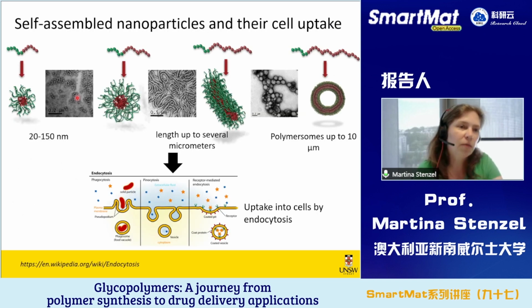But what is even more interesting when we use block copolymers is that we can tailor the size and the shape. So if we start off with two small blocks, we might get very small micelles, like shown here in that TEM. If we make this hydrophobic block longer, we end up with bigger micelles until we come to a point where we obtain cylindrical micelles. So now we get elongated structures, or if we make the hydrophobic block even longer, usually we end up with polymersomes. So the size and shape of these nanoparticles influences very much how they interact with cells.